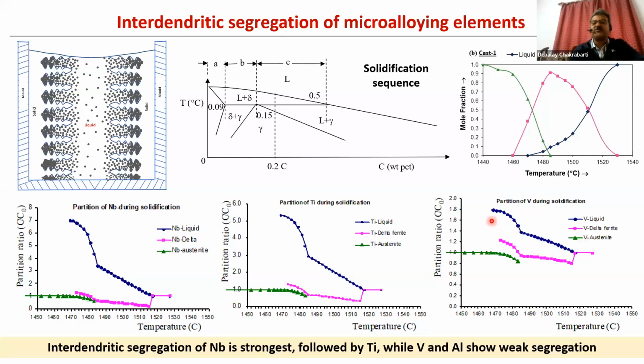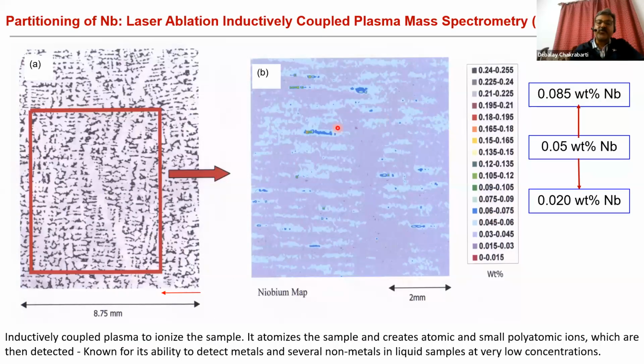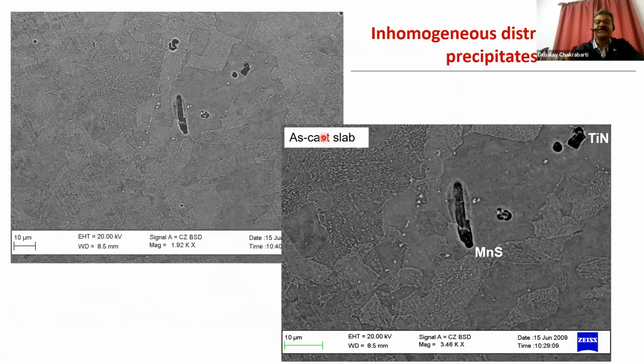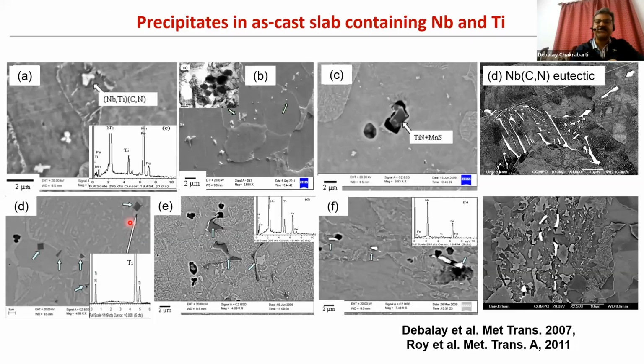Whereas vanadium is much less prone to segregation, and it segregates a maximum of 1.8 times, which is only in ideal condition. In actual condition, it is even below. So this is what the niobium segregation looks like. In the as-cast structure, you see the dendritic structure, and niobium is seriously segregating. In some regions, like the interdendritic region, the concentration of niobium is much higher because it is prone to segregation. As a result, we see non-uniform precipitate distribution. Where niobium is more, there niobium precipitate is more. You see all these white dots are precipitates, and in the middle of this image, there is a large number of precipitates, but in the surrounding region, the precipitate density is very low. So this is the outcome of segregation. It creates a non-uniform precipitate distribution.